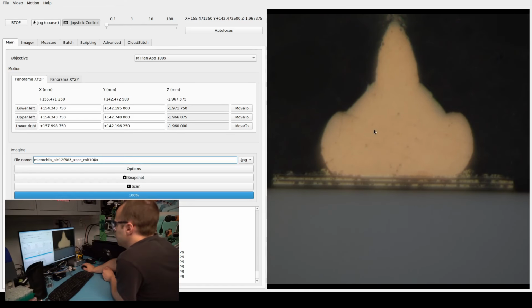And now we're taking a close-up of one of the copper ball bonds. These are formed by taking a small copper wire and striking an arc to it in a reducing atmosphere to melt the tip of it into a sphere. And then a needle presses this down onto the bond pad, and ultrasonic vibrations are applied to essentially friction stir weld the wire onto the surface. And we can see there's a little bit of squeeze out at the top metal layer where when the ball was applied, it slightly deformed the aluminum.